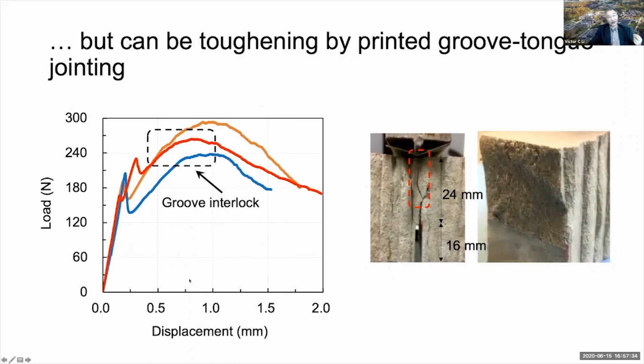The weakness of the interface can be overcome by the introduction of a groove. In this case, we print the groove on the top of each layer. And as the next layer comes along and is printed on top of the groove, the material penetrates into the groove and therefore forms a tongue. A tongue and groove joint provides interlocking, so that when we test the specimen, now the test curve is very different and very clearly indicates the effectiveness of the interlocking mechanism of the groove tongue joint, causing the crack propagation to be much more difficult compared to that of a smooth interface.